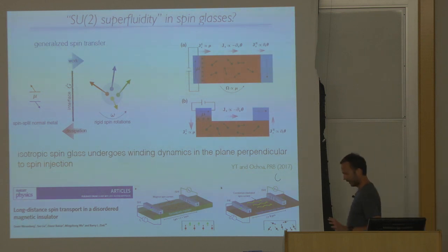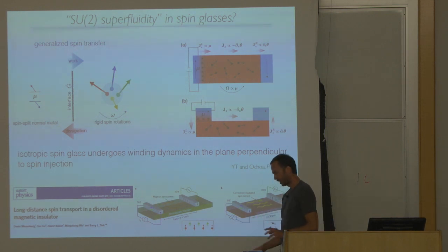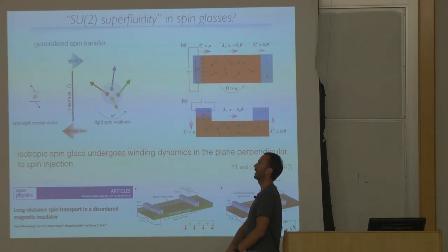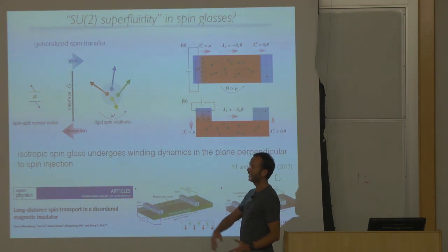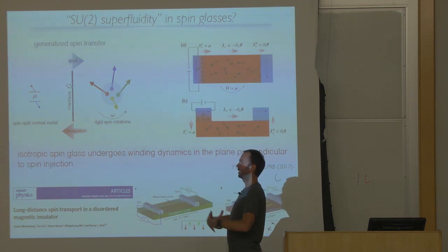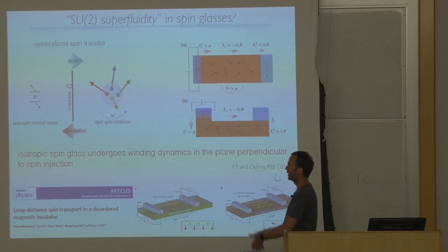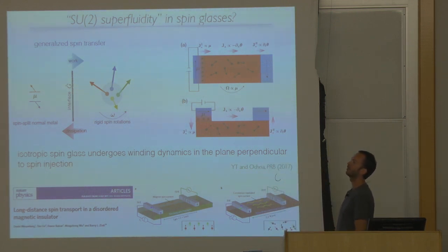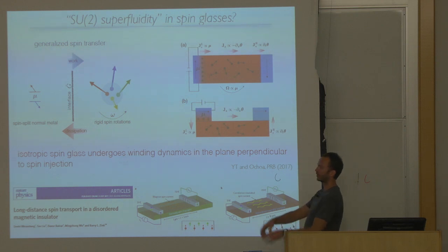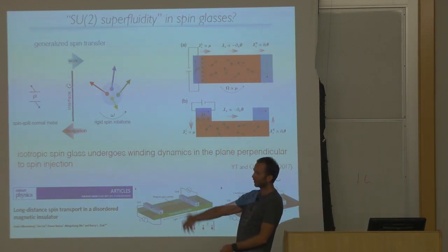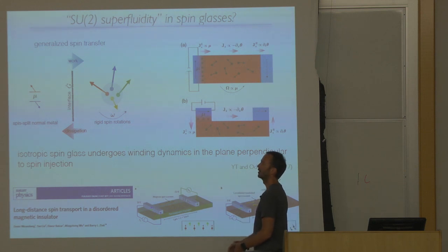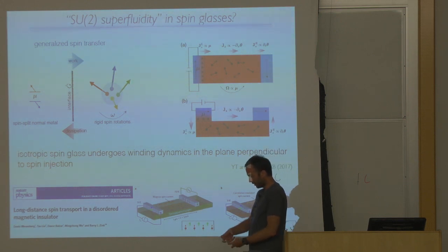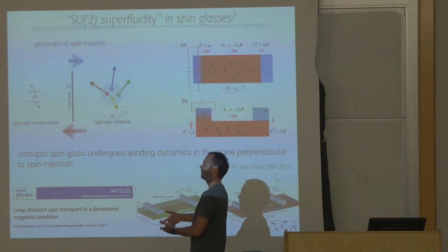Okay, so of course, this is another important issue. There are two types of dissipation in the system. Phase slip, but there's something that I completely shoved under the rug. Anytime you have dynamics in this system, there is dissipation because the environment knows about this dynamics. In magnetic systems, typically at low frequencies, that's Gilbert damping. So there's always dissipation that's proportional to some material-dependent parameter times the local frequency of this dynamics, integrated over. The moment you have a steady state process and the system is doing something useful, there will be dissipation. Static configurations do not dissipate, only the phase slips.